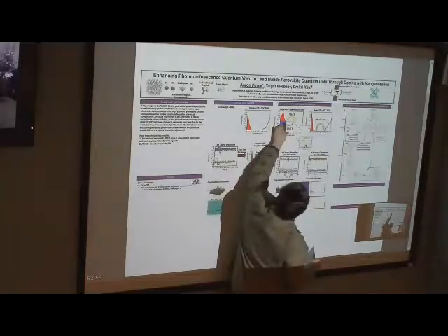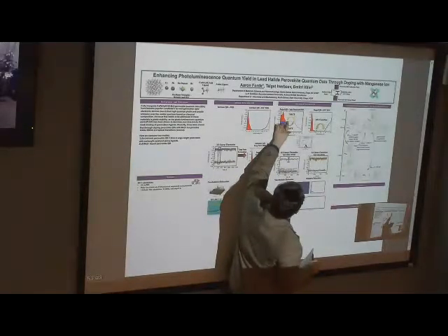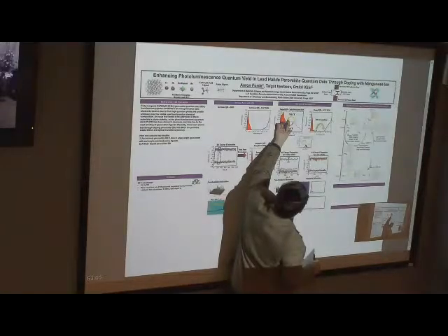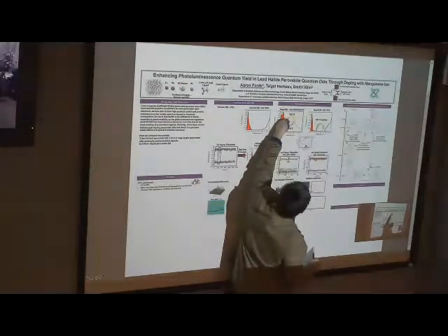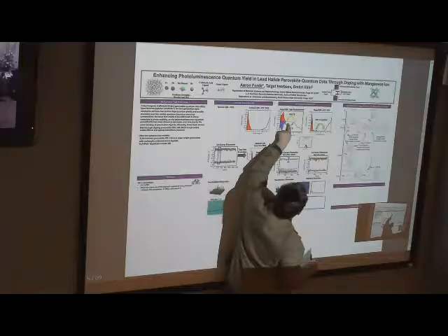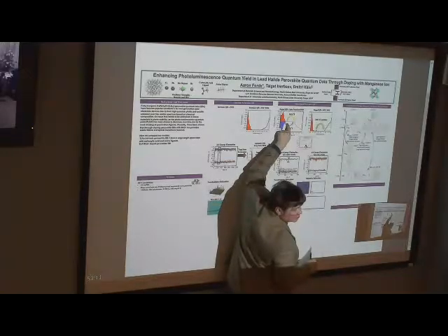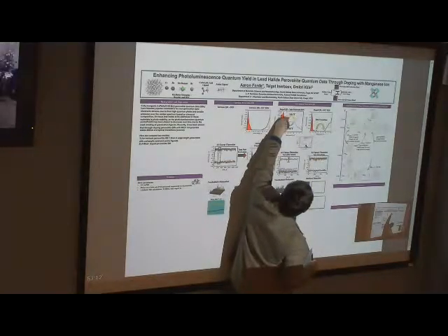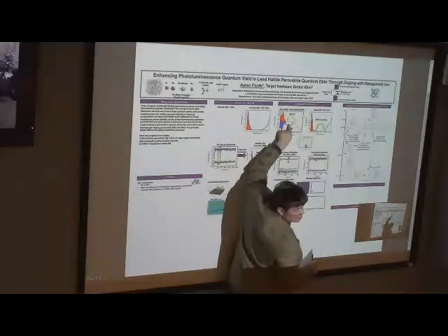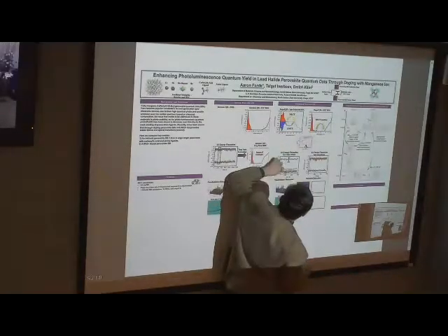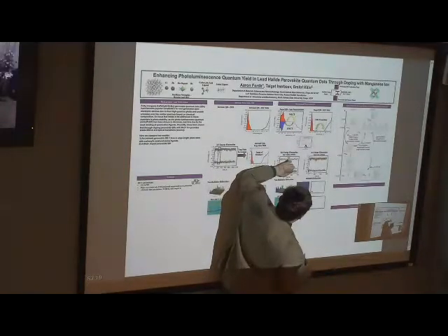So there are several unpaired states, and the density of states in the spin polarized case is unsymmetric. There are some alpha states, and there are no beta states at the same energy. There is something going up here and nothing going down. These alpha states contribute to the spectrum and some additional fluctuations.